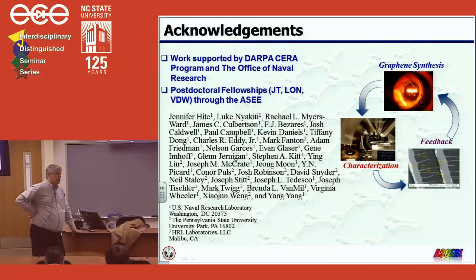What he does is he patterns the sample to make these small edges, these ribbons, and then he does very short growths, so that even though the little ribbons he makes are on the order of half a micron, the amount of graphene in it is even smaller. And he's claiming that he's getting a band gap there, although there's certainly a lot of controversy in that. We haven't tried it. I think it might be interesting, especially to pattern the graphene, to study more about what happens on these other surfaces. We had a brief discussion about that earlier this morning.